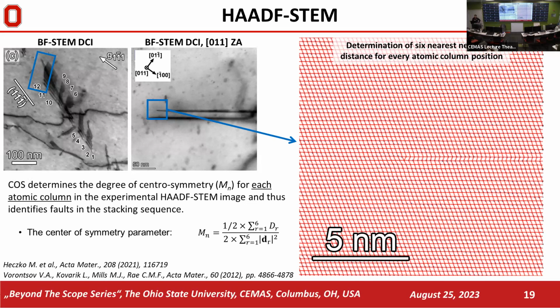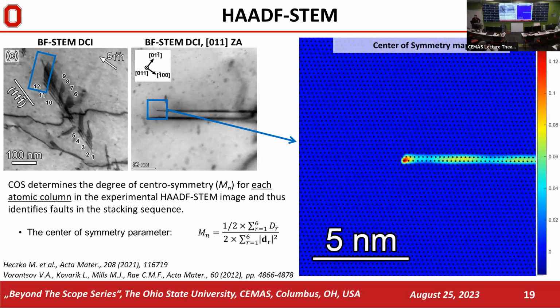So we can use center of symmetry. We can calculate center of symmetry for each atomic column, and basically it calculates how far every atomic column is from the ideal crystal. So you calculate the parameter, and it can visualize. It's very sensitive to changes in stacking sequences. So it can highlight what kind of defect you are looking at. So here, this is a simple Shockley partial dislocation, which is bound to a simple intrinsic stacking fault.